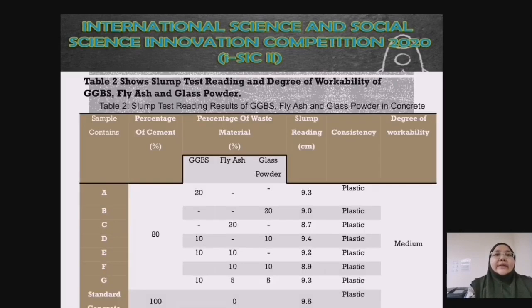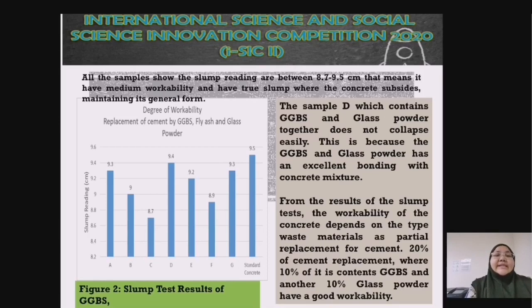This is data for the slump test result. All the samples for the slump test were between 8.7 to 9.5 cm. That means it has medium workability and has true slump, with the concrete subsiding while maintaining its general form. From the graph, sample D, which contains GGBS and glass powder together, does not collapse easily. This is because the GGBS and glass powder has excellent bonding with concrete mixture. From the result of the slump test, the workability of the concrete depends on type of waste material as partial replacement for cement. 20% of cement replacement, where 10% of it contains GGBS and another 10% contains glass powder, has good workability.